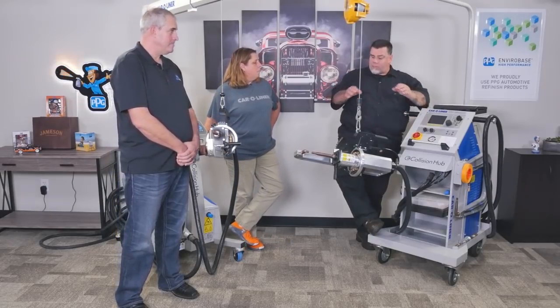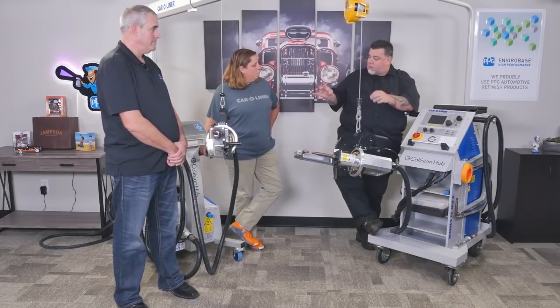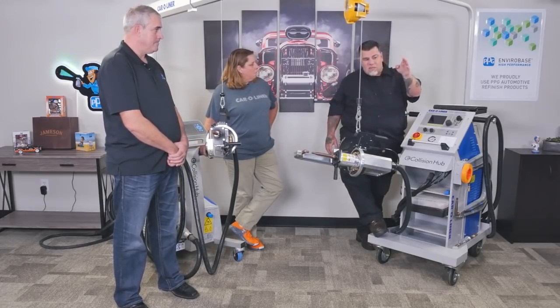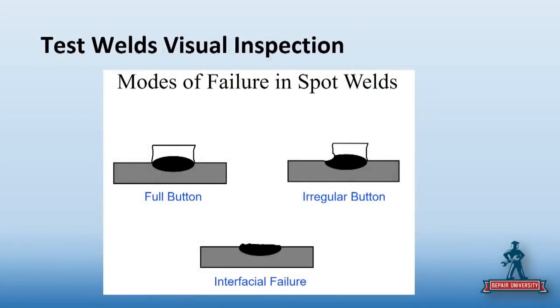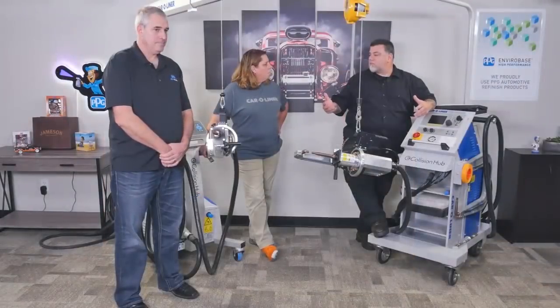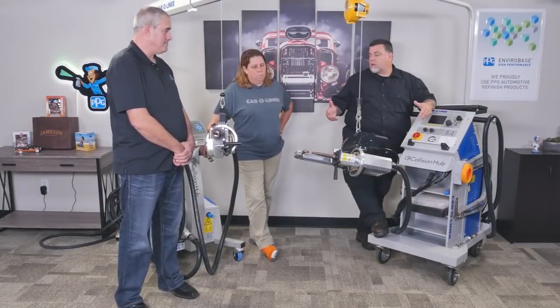It had enough applied pressure that the outer panel has a hole and the inner panel has a whole chunk of material there. That's the full button. Irregular button is obviously that one there, where that didn't pass. The tips are misaligned, part of the tip had contaminants on it, you didn't clean the panels right, it wasn't clamped together. It's an irregular button. And an interfacial failure is where there was no welding at all. In plastic repair, they usually call that, to remind people, a cohesive failure. The adhesive material failed itself, it didn't stick to itself. An adhesive failure is that it didn't stick to the panel; it wasn't set up right. But a cohesive failure is that interfacial failure.